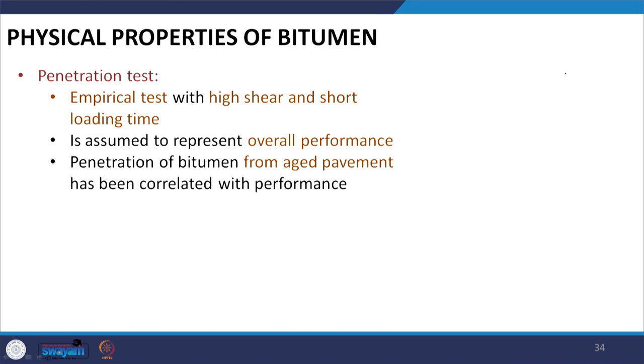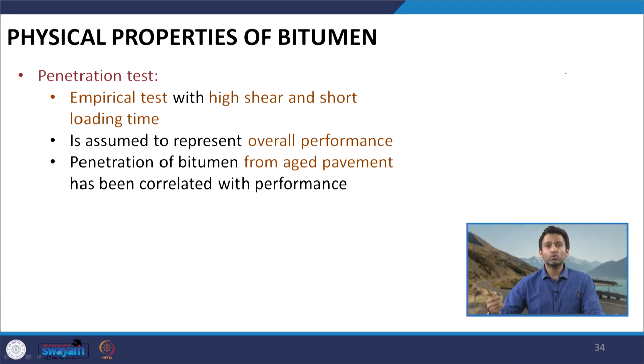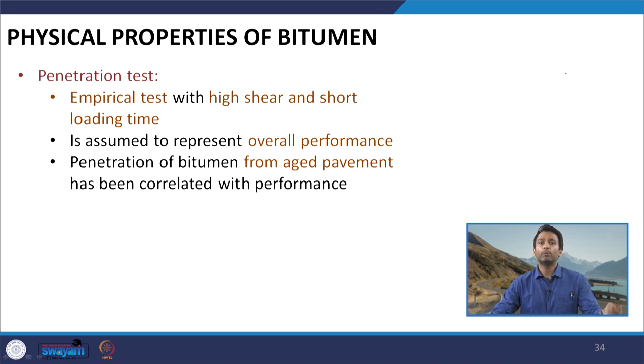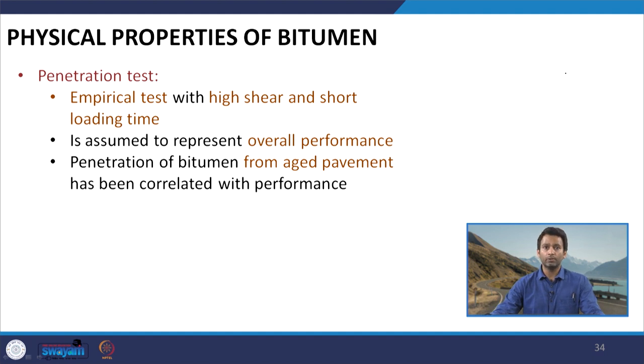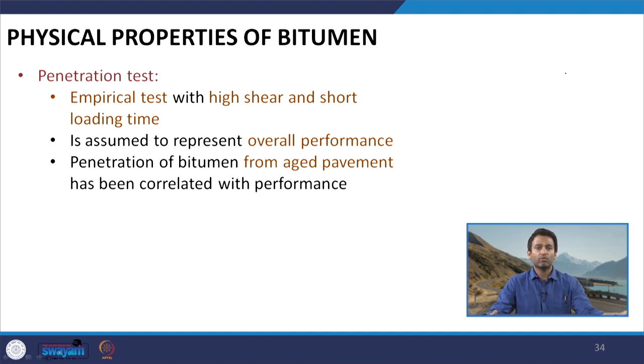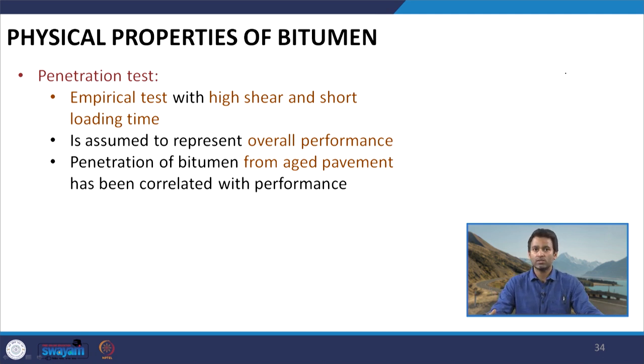Penetration test is an empirical test and in this test, the bitumen is exposed to very high shear for a very short loading time, which may not be peculiar to vehicular movement in the field. However, since it is an empirical test, we are only interested in results and whether they can be related to some distresses in the field.